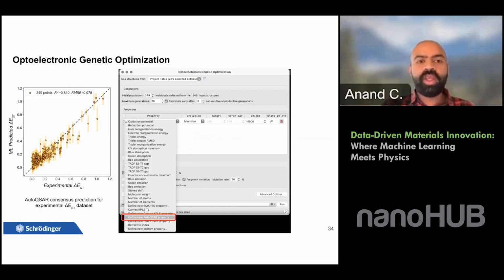So in this particular case, genetic optimization is a very powerful technique. For example, here we trained the AutoQSAR model for the delta EST value. This is an experimental value for the energy difference between the singlet and triplet state for optoelectronic molecules. And we trained the AutoQSAR model for this particular property. And we want to minimize this delta EST value to 0 for this optoelectronic application.